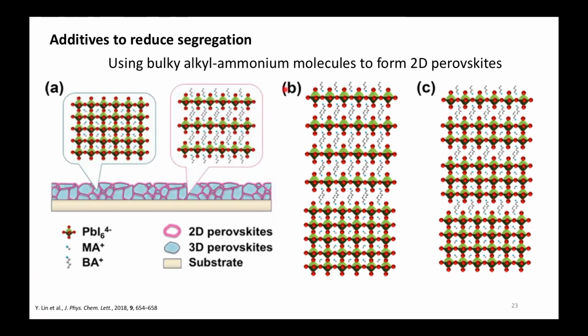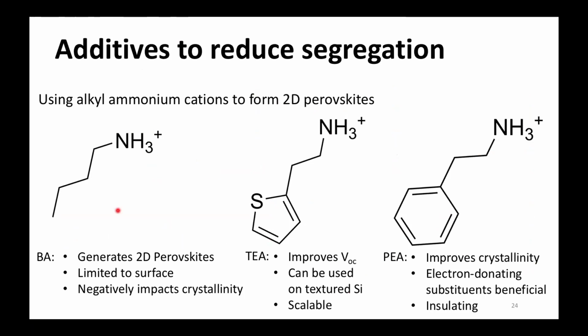And they can do that by forming these 2-dimensional structures. So you can imagine that you have a big crystal at one side, and in between you have a layer of these 2-dimensional perovskite structures with these longer tail alkyl ammonium molecules. So in that way, you can change the material between the crystals. So you can tune that by using alkyl ammonium additives. Butyl ammonium has been used, this thiophene molecule, but especially this phenylethyl ammonium additive. So that gives the 2-dimensional perovskites in between the crystals.